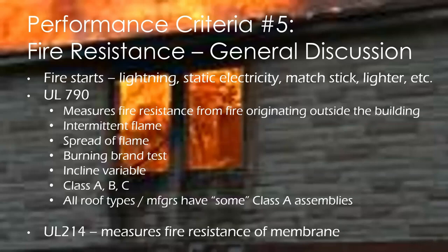When we look at intermittent flame, this evaluates the resistance of flame penetration. So up to 15 cycles of 2 minutes on, 2 minutes off of direct flame applied to the deck. Class A represents no sustained flame under the roof or burning brands for 15 cycles. Class B, no burning brand or no spread of the flame for 8 cycles.